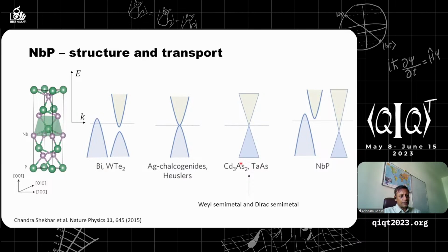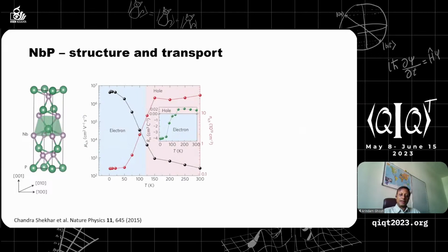Now, why is this such an important, interesting property? Because of the linear band structure, the electrons in these materials can actually go around the disorder very easily. They can bypass the disorder and don't get scattered by it very easily. As a result, the electrical mobility of charges in these materials can be extremely high. The mobility is usually expressed in centimeter squared per volt per second. You can see the mobility can be as high as 10 to the power of 7 at a lower temperature of about 50 kelvins or so.